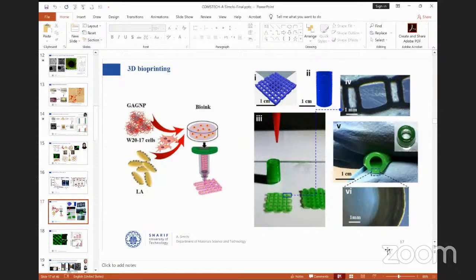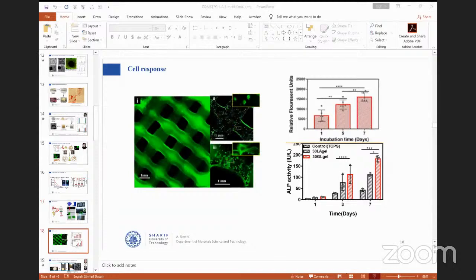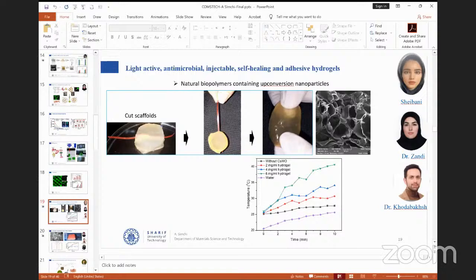And then we use these materials. We did a lot of cell response and cell studies and in vivo studies. The result was very interesting. First of all, we have shown that the cells stick to the surface and are alive in the matrix of the printed scaffolds. As you know, bioprinting has a challenge to load cells inside and have live cells after bioprinting. So the cells are alive. And by using ALP activity, as you saw in the right-hand side figure down, the ALP activity is high, therefore the cells are active, they can proliferate and do bone regeneration.